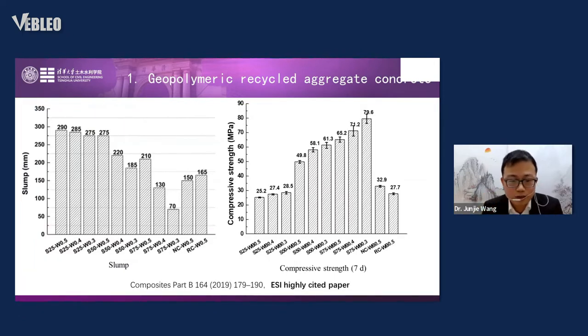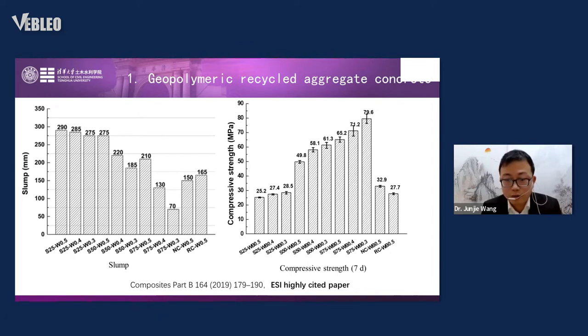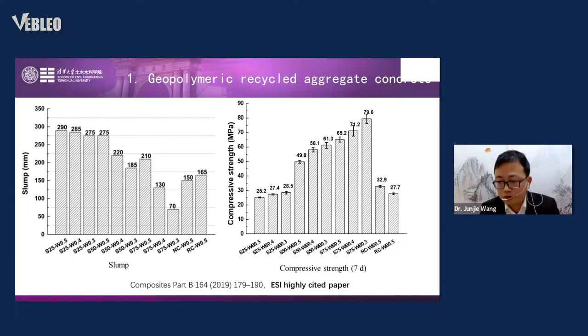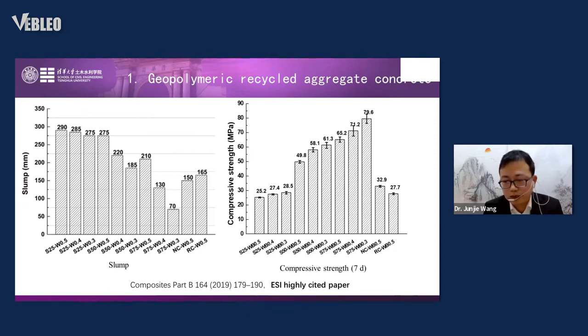The results show slump and compressive strength of the mixes we studied. The slump of most geopolymeric concretes is actually better than normal and recycled concrete. The compressive strength is much higher, especially when the GGBS percentage is 50% or 75%. We published the relative results in Composites Part B, and it has been cited as a highly-cited paper.